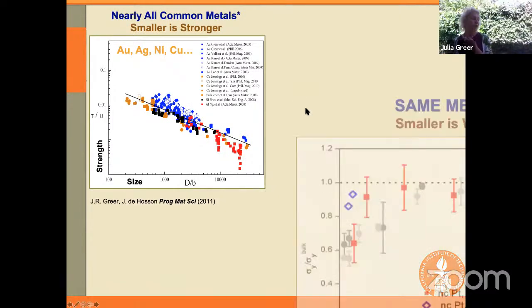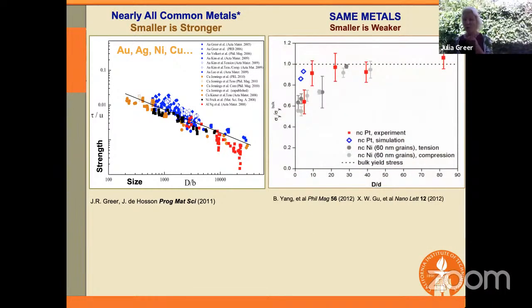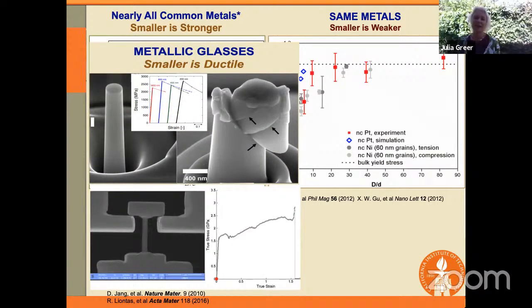So the same metals, the same gold, the same nickel, the same platinum, this is a more modest size effect because it's not plotted in a log-log space. But nevertheless, it shows you that when you reduce the dimensions of nanocrystalline materials, even though they're chemically the same, their strength becomes lower. Now, the size effect manifests itself in other properties.